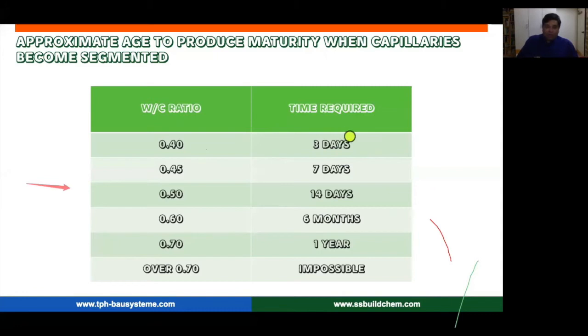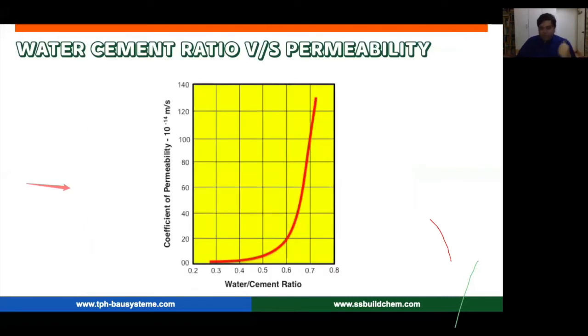Now, if your water cement ratio is say somewhere around 0.5, 0.6, you can see that the time taken is almost 14 days or 2 weeks to about 6 months for all the capillaries to be segmented. So up to that time, your concrete will actually allow a lot of the deleterious materials to enter into the concrete. So the simple thing being, simply reduce the water cement ratio, and the permeability of your concrete will decrease, or the water tightness of your concrete will increase automatically.